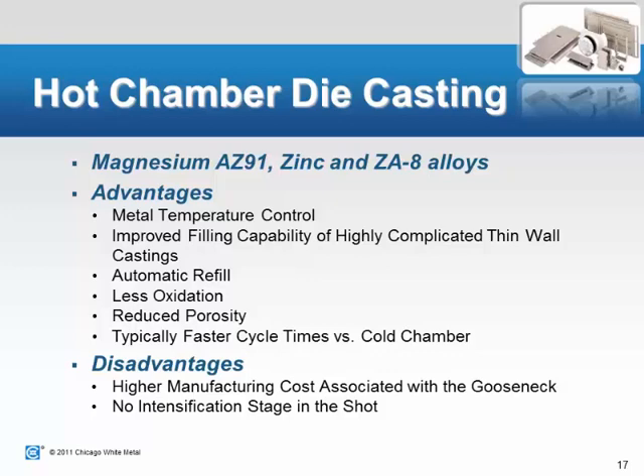So hot chamber die casting, again, is for the lower melt alloys. So the AZ91 magnesium, the zinc family of alloys, as well as the ZA8, which is the 8% aluminum alloy. It doesn't have enough aluminum to push it to the cold chamber.